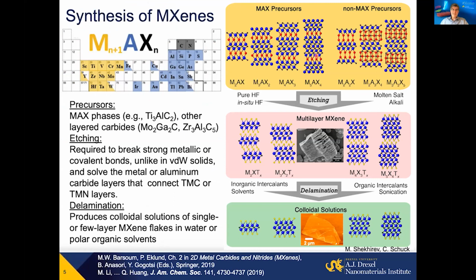So these materials are layered, but there are strong metallic or covalent bonds between them. And if you take an acid, you can dissolve this metal, for example, aluminum, releasing two-dimensional states and initially making something looking like thermally extended graphite or vermiculite clay, which are basically now layers of carbide with weak hydrogen or van der Waals bonds between the layers because the surface gets terminated by oxygen or OH. And this is how, working with Professor Barsoum and our student Michael Naguib, we produced first MXenes and published it in 2011.